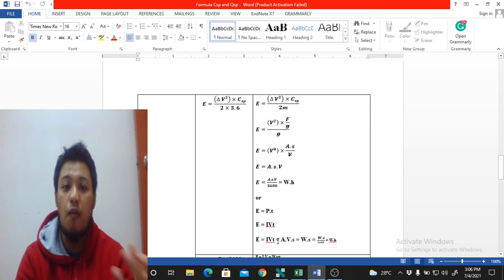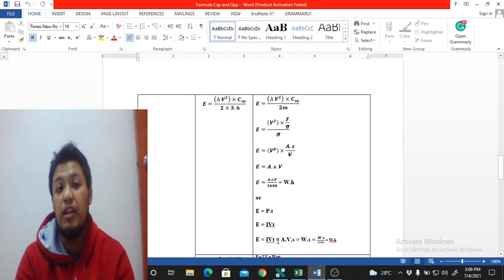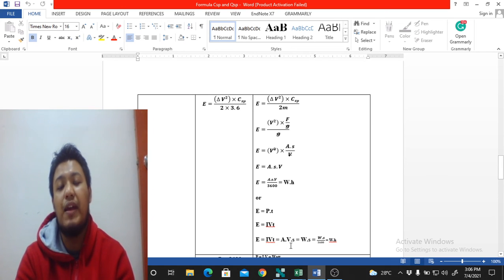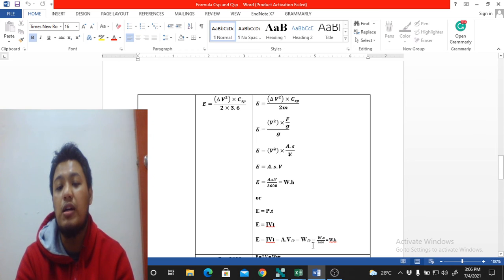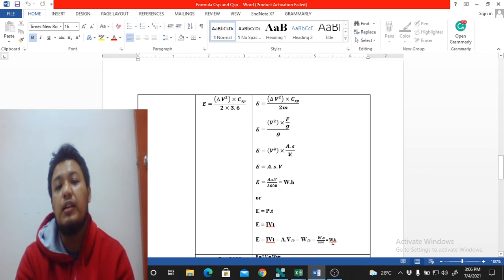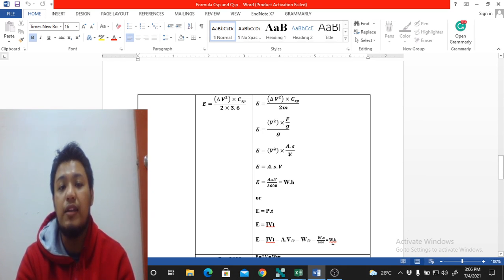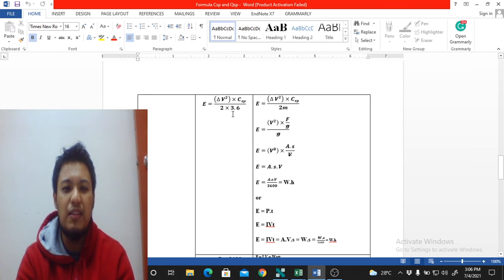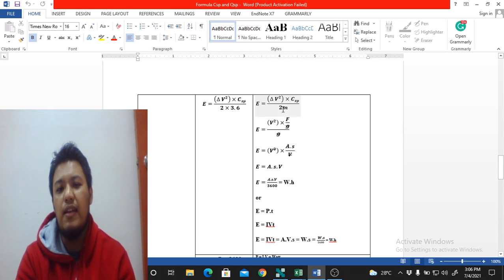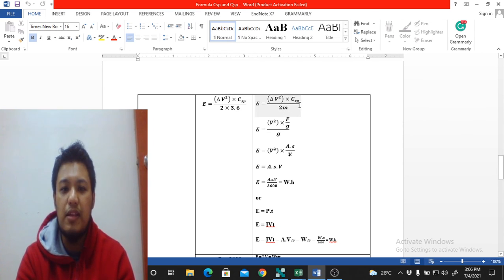Many papers also use the formula E = C_sp · ΔV² / (2 × 3.6), where C_sp is specific capacitance in F/g and ΔV is the voltage window. Dividing by mass, we get V² × (F/g) / g. Since F = A·s/V, the V² cancels one V giving A·s·V, which is watt·second. Dividing by 3600 gives watt·hour, and normalizing by mass gives Wh/kg.